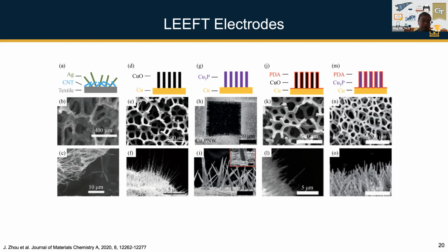But the biggest challenge for pushing the LEEFT technology to be a standalone, high performance disinfection process is really the electrode design for the nanowire modified electrodes. We started with silver nanowires, copper oxide nanowires, and then the one I just demonstrated to you is the PDA coated copper oxide. We also changed the material from copper oxide to copper phosphide, because copper phosphide is a little bit more stable than copper oxide. But so far we have demonstrated that the electrode can be used for about 10 days to 2 weeks of continuous operation, but with synthetic water, basically DI water, very clean water, DI water with model bacteria in a very controlled environment.